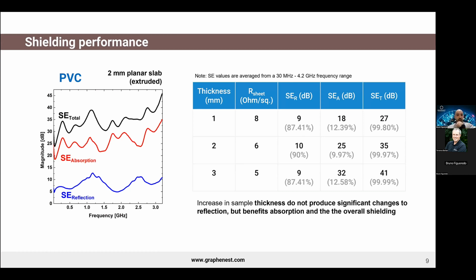So let's now take into account the table on the right, where we have the results of 3 different thicknesses: 1, 2, and 3 millimeters. As can be seen, changing the thickness does not change much the surface resistivity. So the surface resistivity is among 5 to 8 ohms per square. So less than 10 ohms per square. And that is why the reflection mechanism has an almost identical role in the 3 samples. So as you can see, in terms of decibels, it is 9 to 10 decibels of reflection.